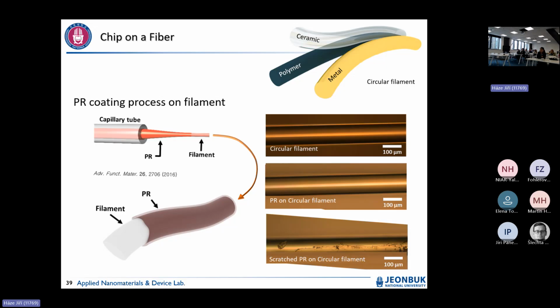some core of optical fiber. The optical fiber core is definitely made of glass or quartz, right? It's a good substrate core, and it has a really nice surface, right? Then we coat the desired polymer, for example photoresist. Right at the coating, it's really hard to identify what's happening. But my student carefully scratched it out, and we found it's a nice coating on the surface.